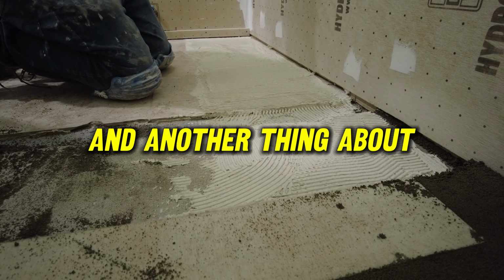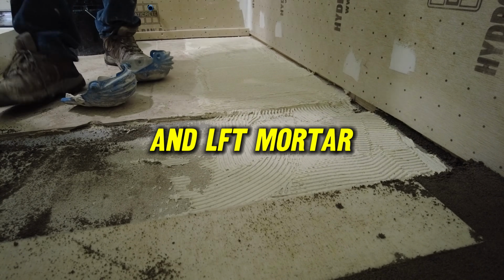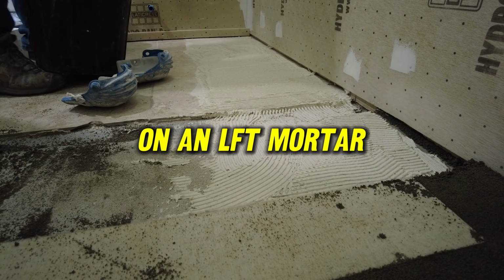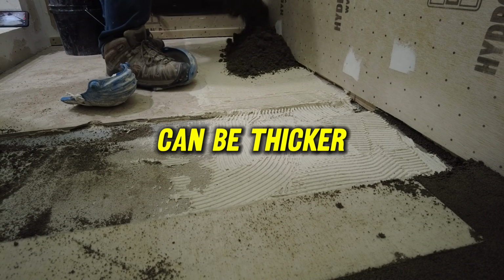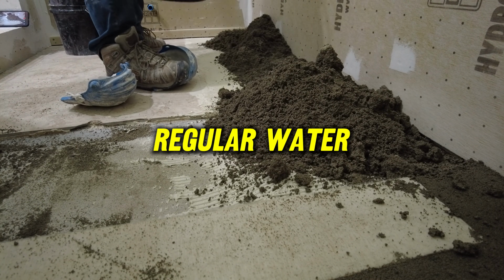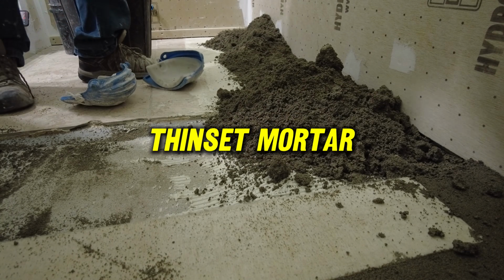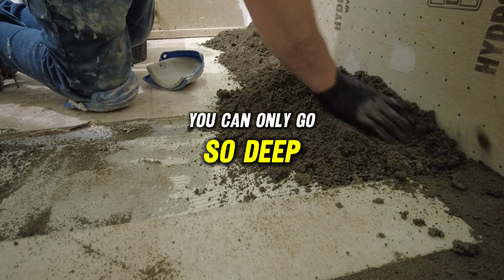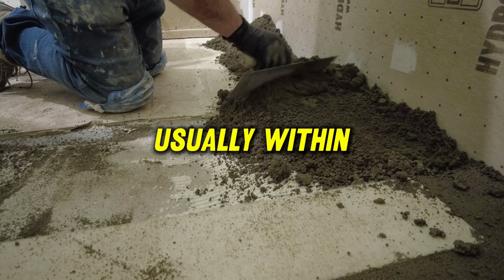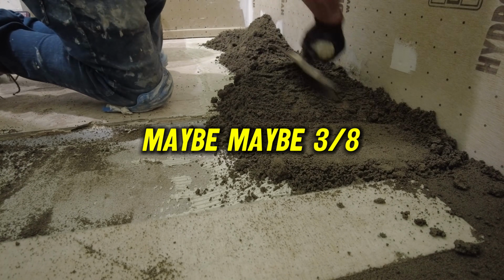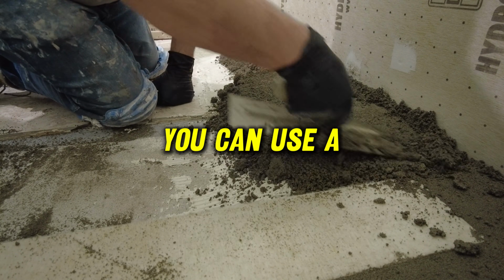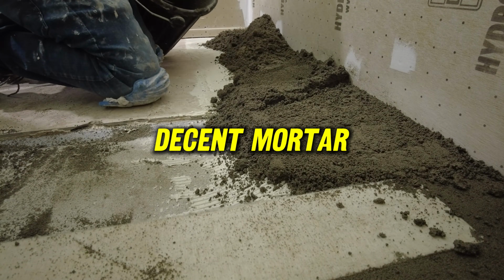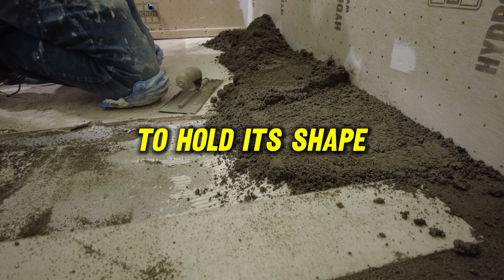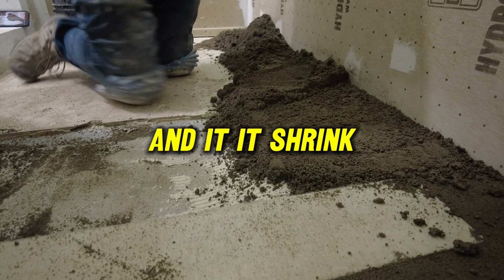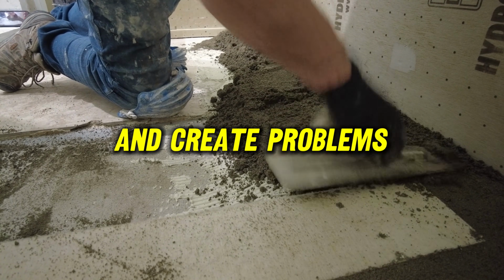It'll stick to it, but it's probably better if you use Thinset mortar designed for a larger tile. And another thing about a regular mortar and an LFT mortar, the bond coat on an LFT mortar can be thicker than that on a regular mortar. So if you've got a regular Thinset mortar, you can only go so deep. They all vary, but they're usually within like a quarter inch, maybe 3/8 thickness, that you can use a Thinset mortar before it starts to lose its ability to hold its shape and it shrinks and creates problems.